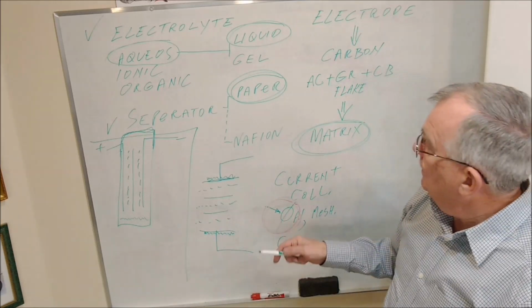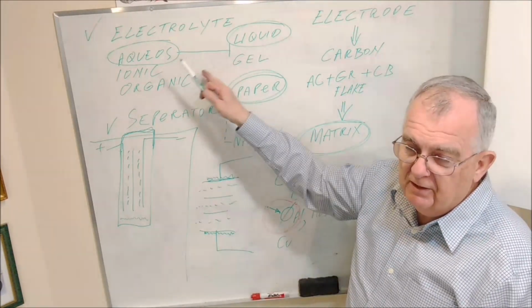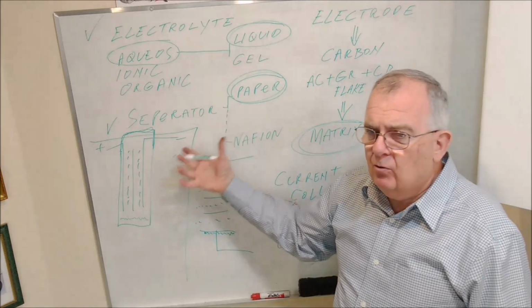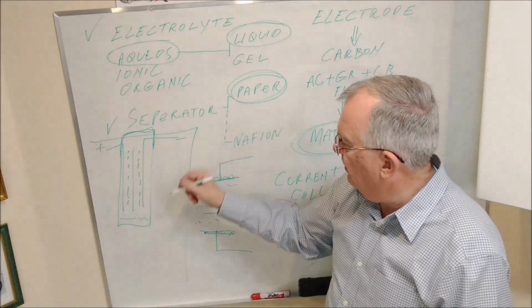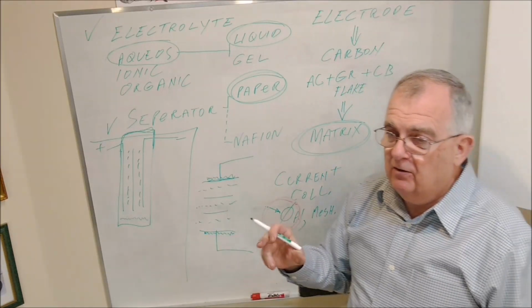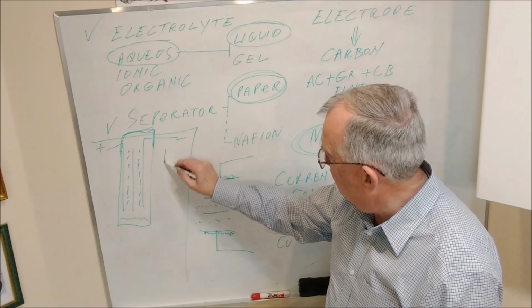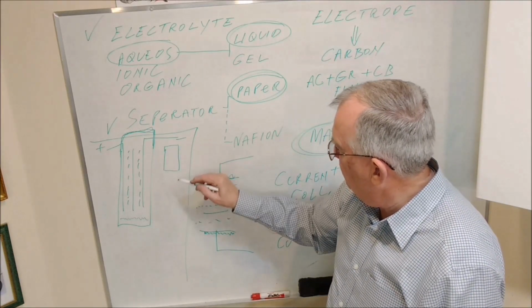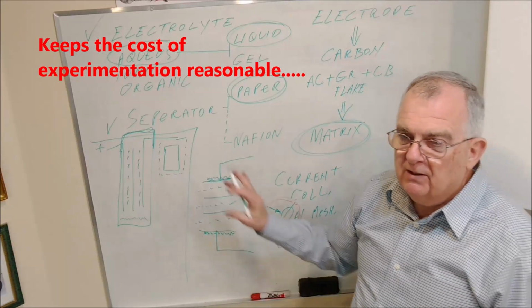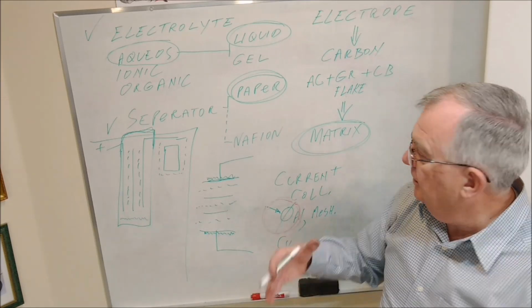When I talk about control, the concentration of the electrolyte, maybe it's not optimized, but keep it constant. The area of the electrodes: we're talking about milliamp hours here in this cell, but it's really milliamp hours, let's say, per square centimeter of area. So define that area for the cell. Pick a constant. You'll see in one of my next videos, the constant that I picked is basically about a 1.5 by 2-inch electrode size. And why did I pick that? Well, it fit nicely in some little polyethylene bags or pouches that I had. But that's a good, reasonable size to look at improvements that you're making incrementally, one at a time.